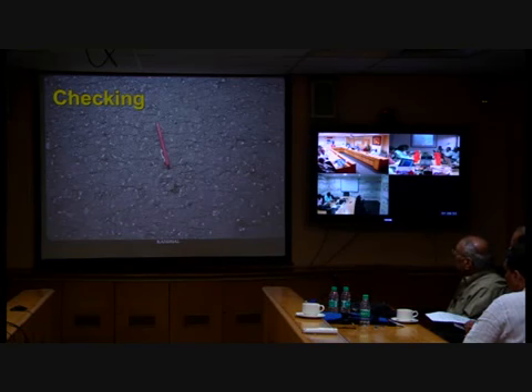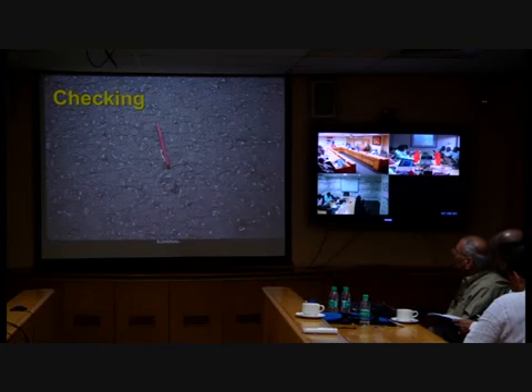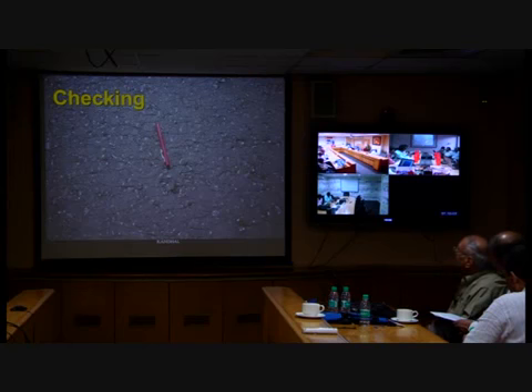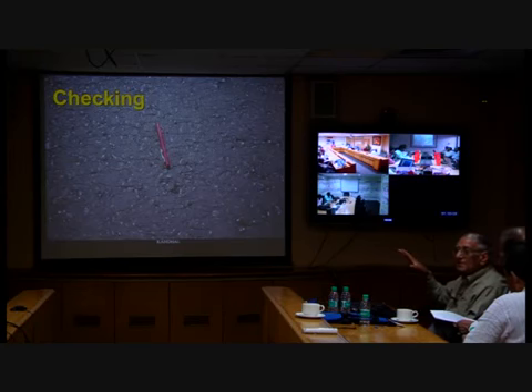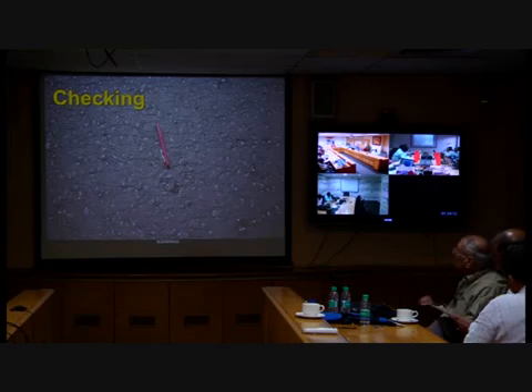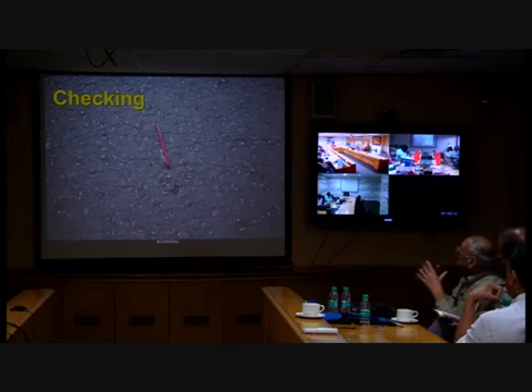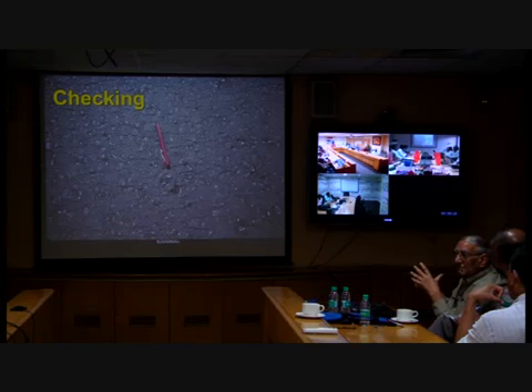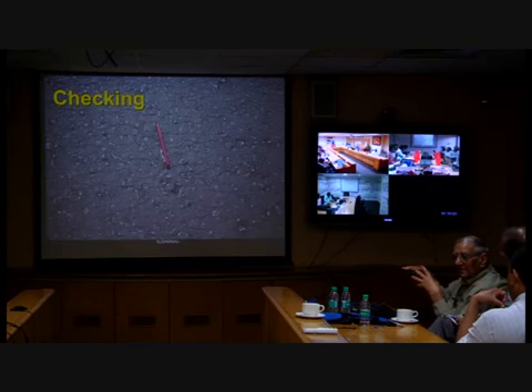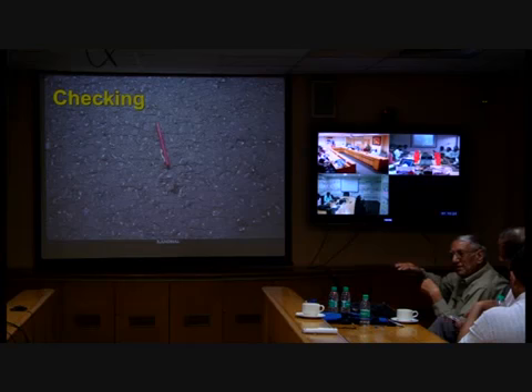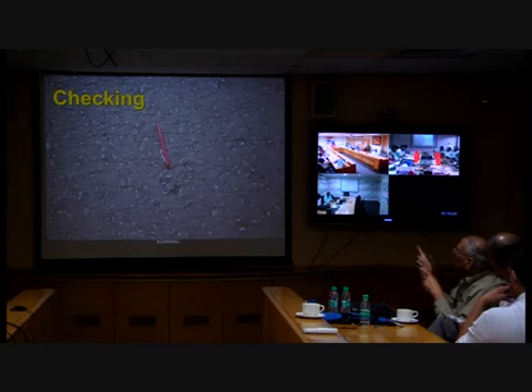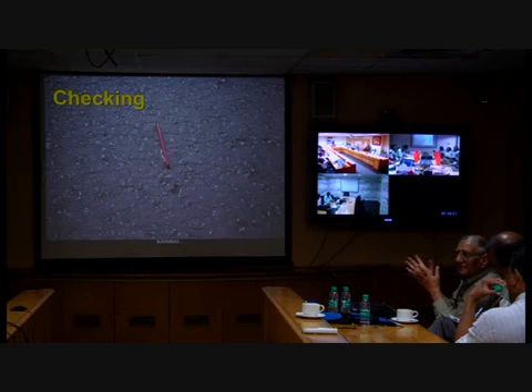during compaction. So what can be the cause of that? We got to do something about the way we are rolling it. So why is it happening? It might happen sometimes because the mix is not taking the weight of the roller. So either I have to back off, so the mix cools down a little bit, and it can take weight. Otherwise, the mix keeps on moving, and it develops these kinds of cracks. Or my mix might have too many fines in there. There are several reasons.